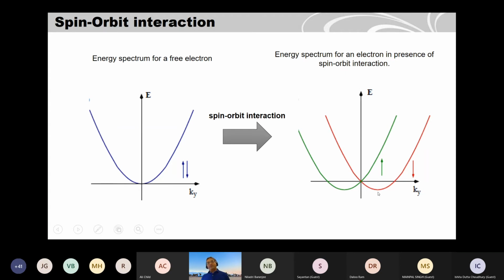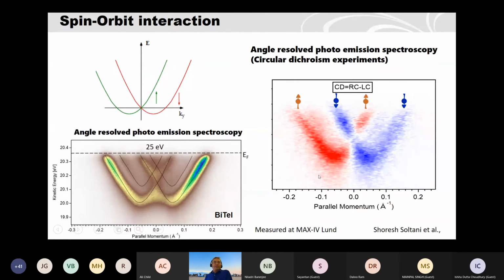This is theoretically fine, but can we see such behavior experimentally? Yes, of course you can. Here we recently measured one semiconductor, bismuth tellurium iodide. It's called a high Rashba spin orbit semiconductor. As you see, spin orbit interactions should split the bands. Here is the angle resolved photoemission spectroscopy measurement showing how the bands are split. You see not only two bands but multiple bands.